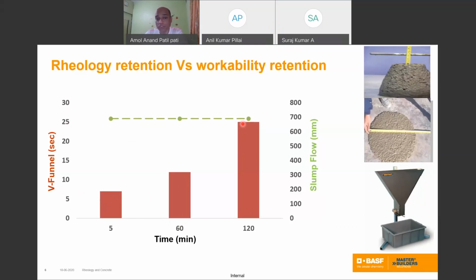So friends, one thing is most important. Suppose you are pumping the concrete from 100-meter height or 200-meter height or other challenging situations. If your transit mixer reaches the site within 5 minutes and you use the concrete, the viscosity of the concrete in terms of V funnel is 7 seconds. Your pumping pressure, pumping operation, finishing, and compaction all have different dynamics. The same concrete at 120 minutes, because of traffic congestion or other issues, or because the RMC batching plant is 20 or 25 kilometers away, you have to transport the concrete anyway. If your transit mixer reaches the site at 120 minutes and you start pumping, the viscosity of the concrete is around 25 seconds.